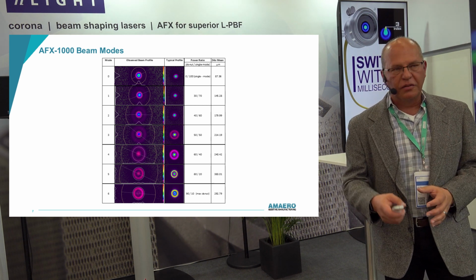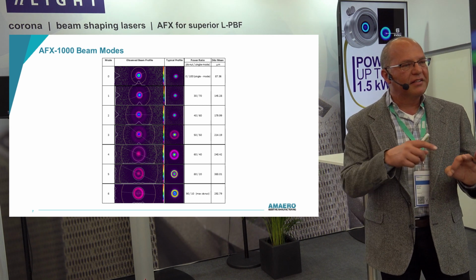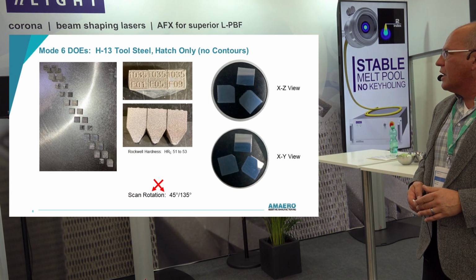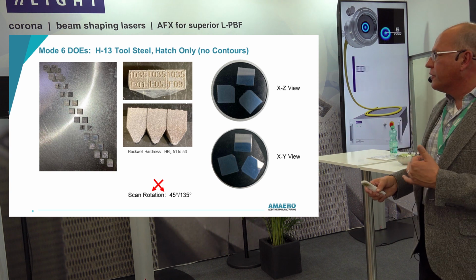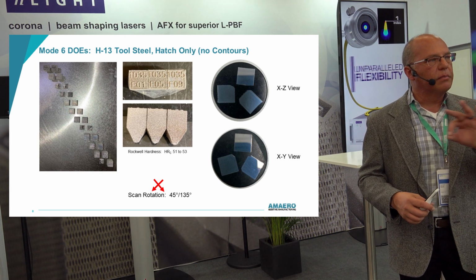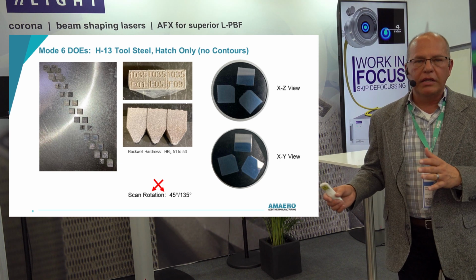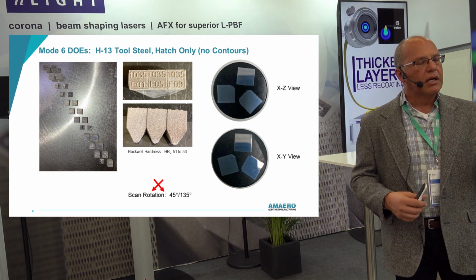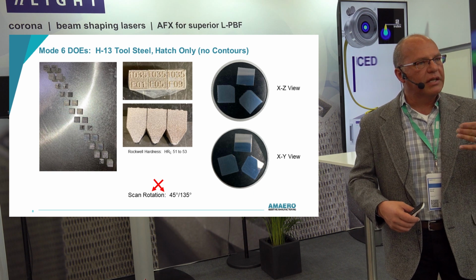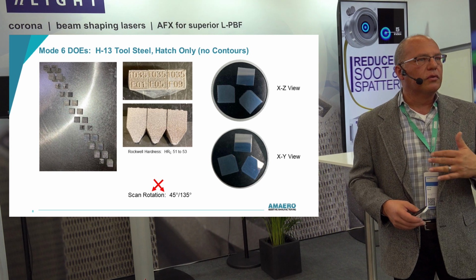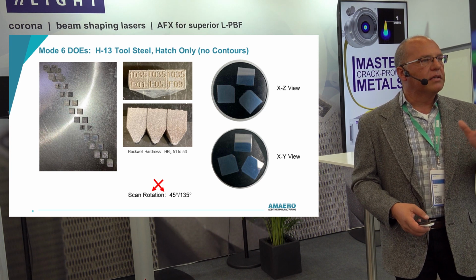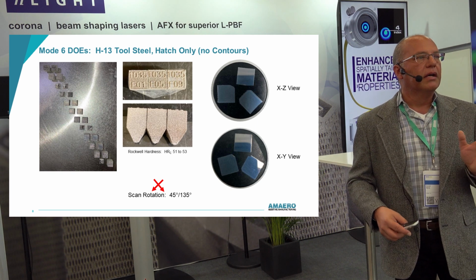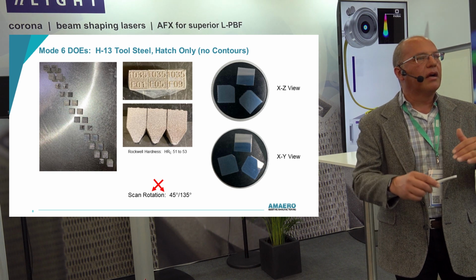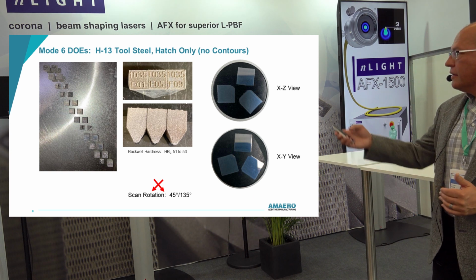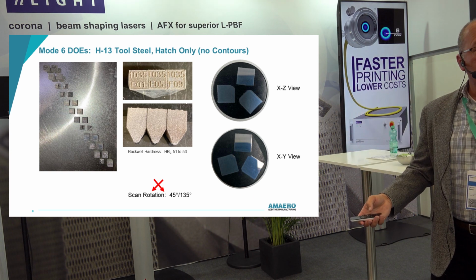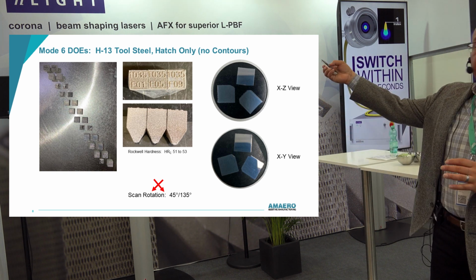I wanted to know what this ring can do for me because it's 300 microns and it's hot on the outside and cold in the middle. So doing some DOEs, and this is hatching only. We didn't do any contouring. The first DOE, we left a lot of the process conditions alone. 30 micron layers, very slow scanning. And in order to look at the microstructure more easily, we just alternated our layers by 90 degrees. Normally we do a 67-degree rotation, but by alternating 90 degrees, it was easier to look at the microstructure and see what's going on. And also that meant that each layer, because we printed 45, 135, each layer engaged the gas flow at 45 degrees. So every layer was essentially the same process condition. And I mean, just these surface finishes alone, again, a 300 micron ring, no contouring. We got great surface finishes. All that labeling was done with the ring also.